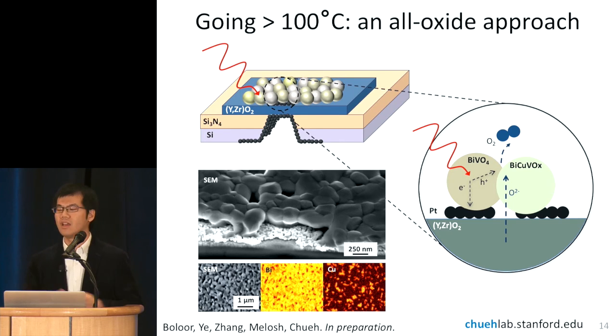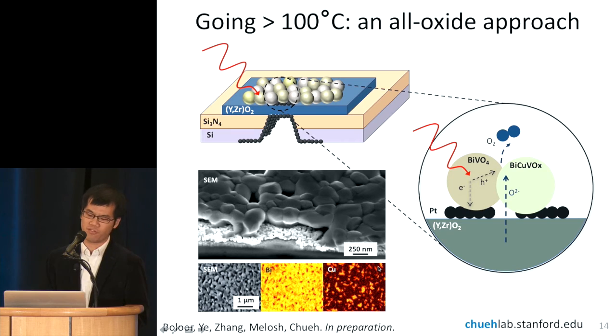We mix that in with the bismuth vanadate. You can see here in the color images, the red images show you the distribution of copper, which is not present in bismuth vanadate. And by mixing the two at the boundary of these interfaces, you have the electron hole pair coming from the bismuth vanadate. You have the oxygen ion as your mobile carrier in the bismuth copper vanadium oxide, and you have the whole thing on a solid state electrolyte.